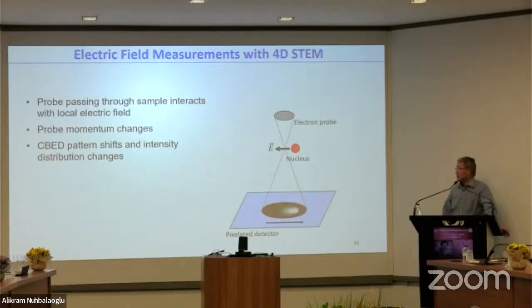So with this, we did expect that when the electron probe passes through the sample, it will sense the nuclear charge, and the field due to the charge is to the left, and then the center of mass of the electron diffraction pattern will move to the right because of attraction.